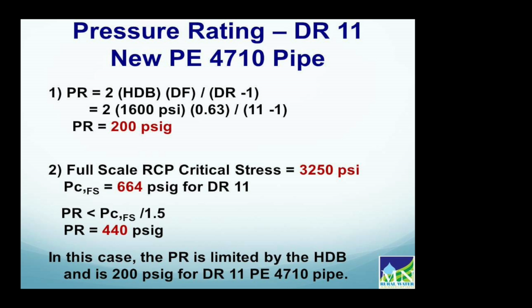Now we're getting to some higher pressures with polyethylene. But how does that compare to the critical pressure? Because again, we don't want to be close to the critical pressure. The critical pressure for this material is 664 psig, about 3 times the pressure rating. Dividing this by 1.5, we get to 440. The pressure rating calculated of 200 is way below the critical pressure, way below the pressure rating limited by RCP. RCP is not an issue with the new polyethylene materials.